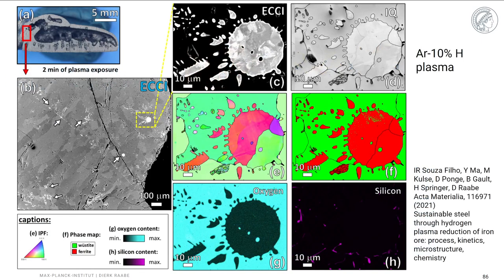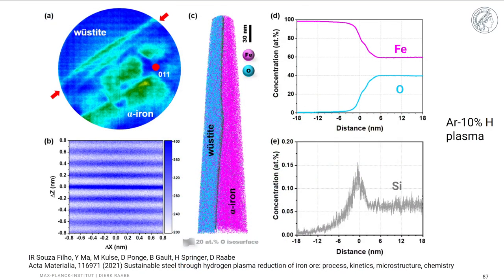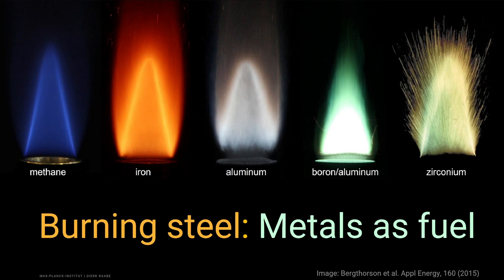And here you see also beautiful microstructures that form under such conditions. And again, we do also here atomic scale analysis and see, for instance, here a very interesting interface between the wüstite and the alpha iron. So this is a partially reduced material with some remaining wüstite. And you see that the silicon that sits on the interface between these two phases seems to play quite a big role. So that, of course, in the further research, we have to take the chemical composition of the oxides into account and the slag metallurgy in the secondary or ladle metallurgy.